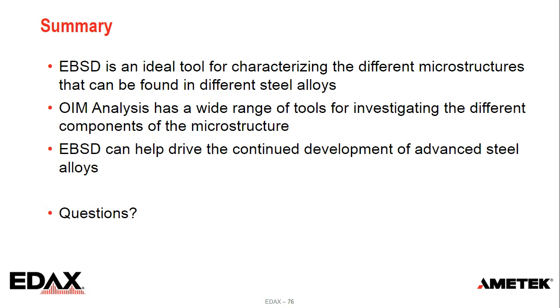The heavier it is, the better it scatters, the better spatial resolution. And it also will depend on the acceleration voltage you're looking at. I mentioned the iron carbides: Stefan Zaefferer and his group at MPI in Germany showed they could go to lower voltages, say 20 to 10 or 12, and could resolve more of the carbides at finer phases.